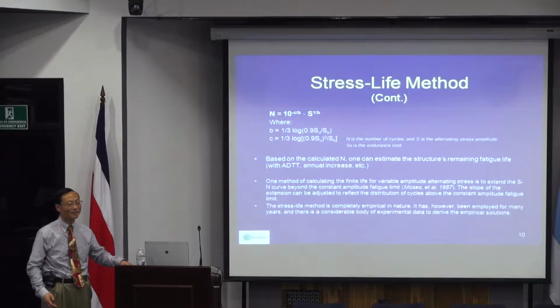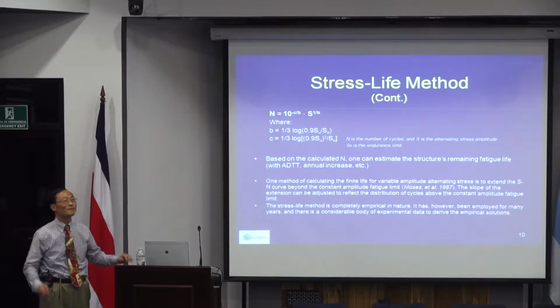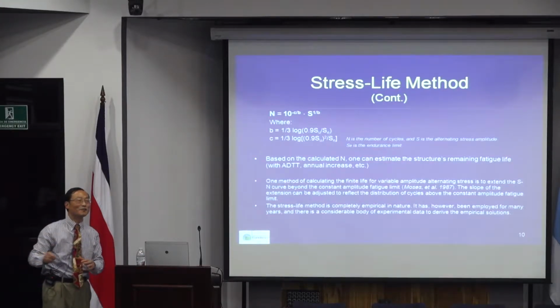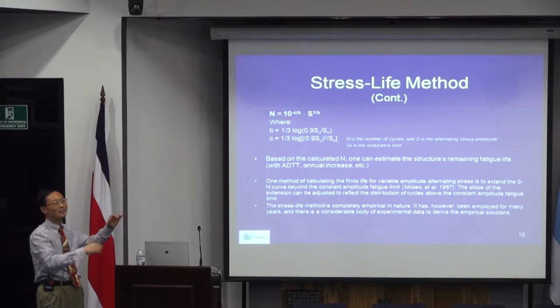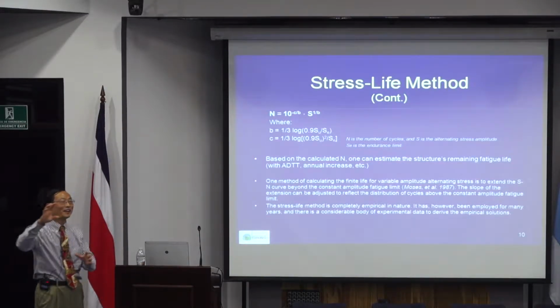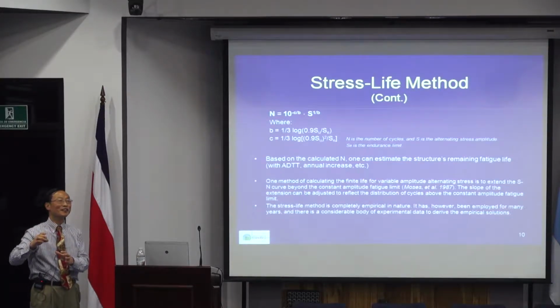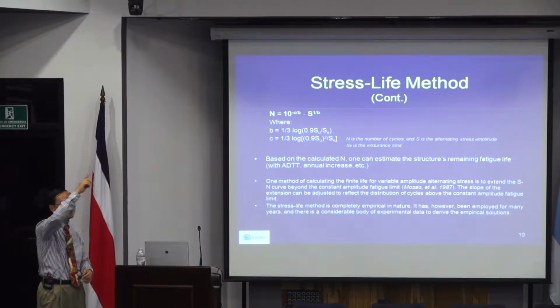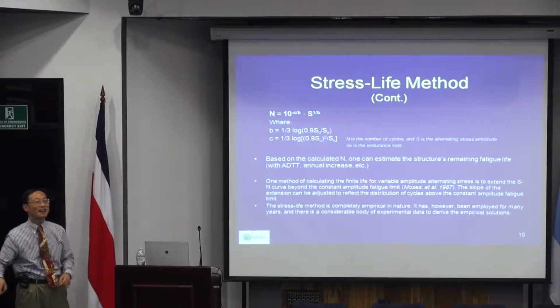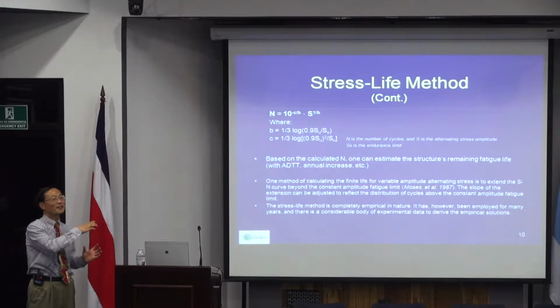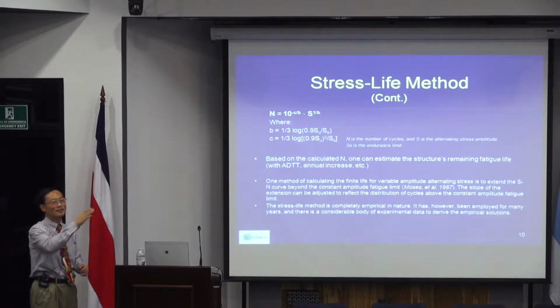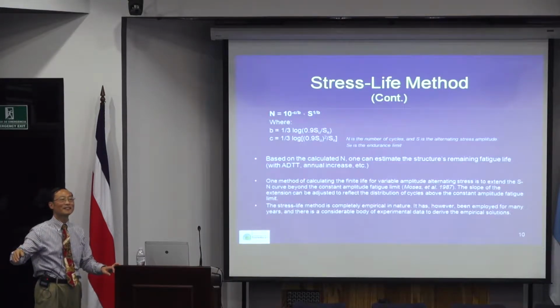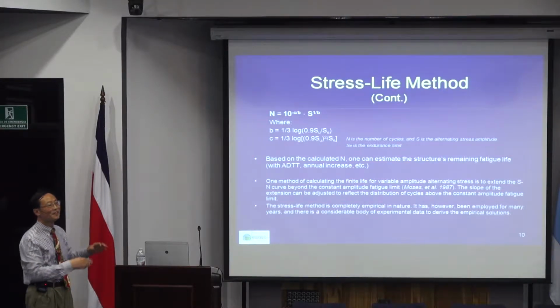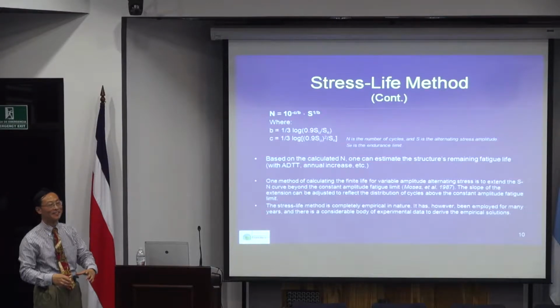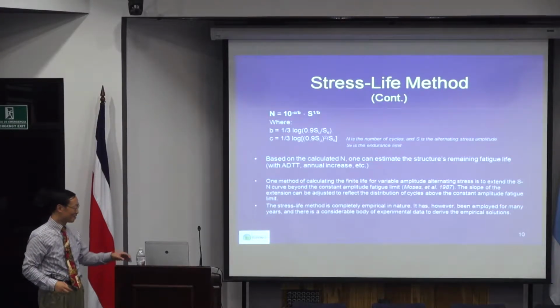Then people looked at bridge design. Actually, there are not too many different details. So they said, let's put them into different groups. For this type of detail, the stress concentration factor is that much, so I put that into a category. Once they have different categories, which already take into consideration stress concentration, they just have different SN curves for each category. In that case, the stress concentration is reflected in the different lines of the SN curve, so the designer will not need to calculate stress concentration. You only need to look at what the detail category is and use the corresponding stress. That's how AASHTO is used.